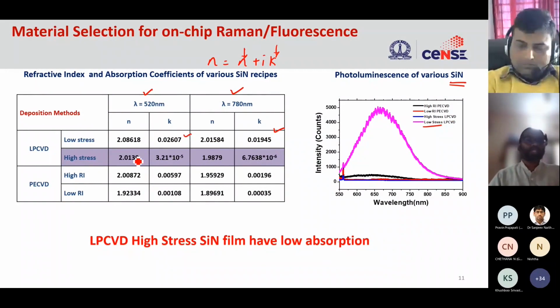However, if you look at this high stress nitride, that shows a very low K value. K values are related to the absorption coefficient, right? The extinction coefficient. So if it is a very low value, you can see here the photoluminescence is very low for the other material as well. So this is all from the thin film characterization.